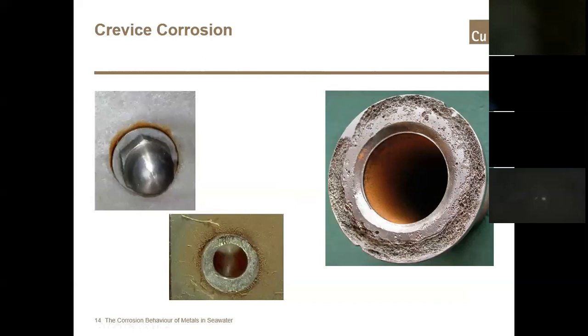We can look at removing the issue of crevice corrosion by using good practice. So it's always good to design components avoiding threaded connections, avoiding sealing tight crevices with welds, and making full penetration pipe welds. Alternatively, local improvements to crevice corrosion resistance can be achieved in areas such as flange faces by weld overlaying. This weld overlaying would be done with more resistant high nickel alloys that would offer better crevice corrosion resistance.